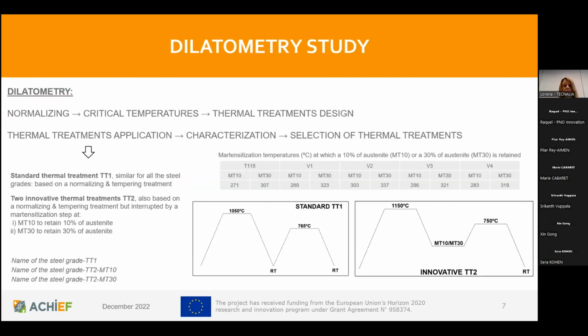Okay, let's see what we have carried out within the dilatometry study. We have started with the application of a normalizing treatment on the steel grades in order to have enough information to be able to calculate the critical temperatures of each steel grade. And then with this knowledge, we are able to design the thermal treatments most suitable to each steel grade. Okay, so then we apply them, we characterize the samples, and based on the results obtained, we select the best thermal treatments for each steel grade.